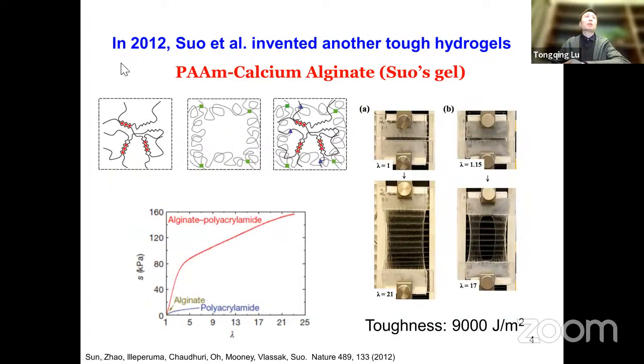After about 10 years, in 2012, Professor Zhigang Suo from Harvard University invented another type of tough hydrogel. It is also a double network hydrogel. One network is the same as in Gong's gel, a PAM hydrogel, and the other network is an ionic network, calcium alginate. They combined these two networks to form a hydrogel, which also has very high toughness. We believe this also is attributed to sacrificial bonds breaking.